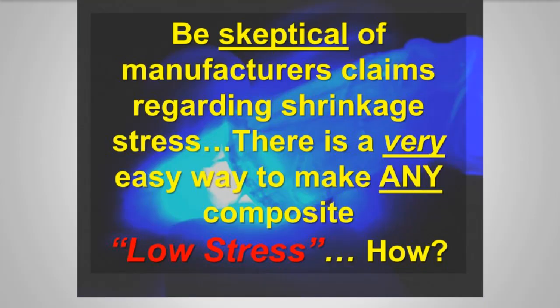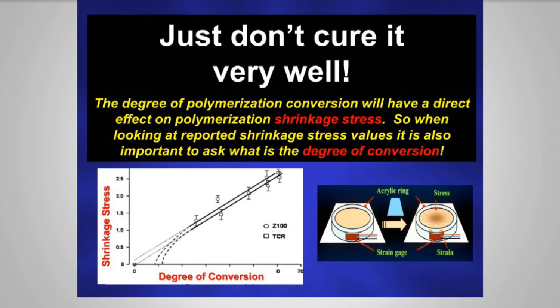And by the way, there's a very, very interesting and very easy way to make any composite low stress. I can go into any of your offices, you can show me what composite you're using, and I can show you in 10 seconds how to make it induce less stress at the adhesive interface. How do you do that? You just don't cure it very well, because the degree of polymerization conversion will have a direct effect on polymerization shrinkage stress. And it's almost a linear relationship. So when you're looking at reported shrinkage stress values, it's also important to ask what the degree of conversion is.